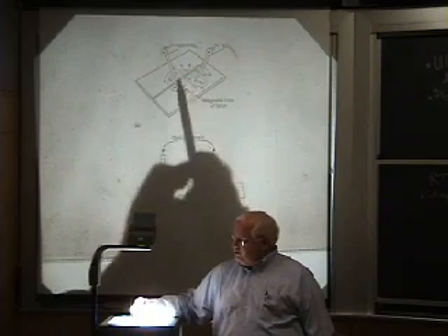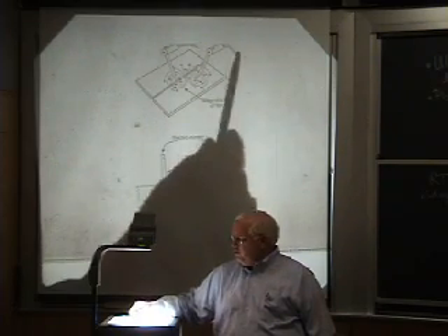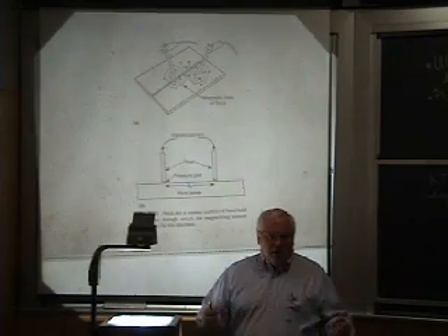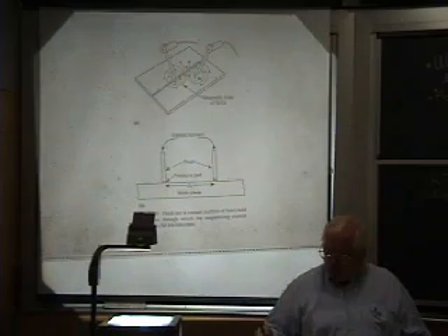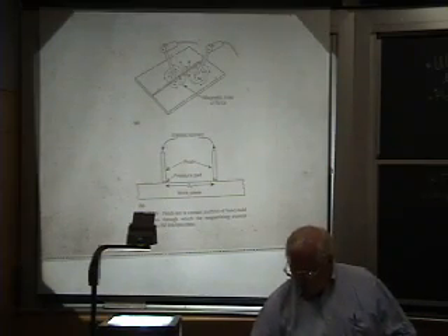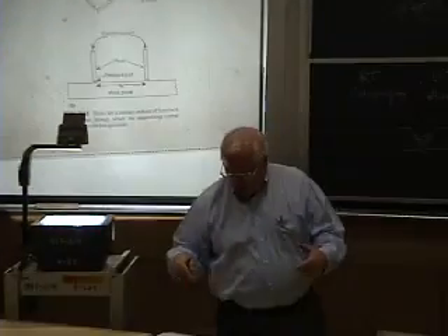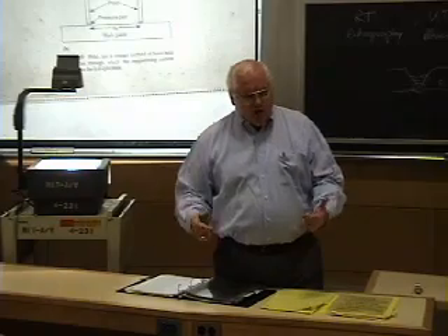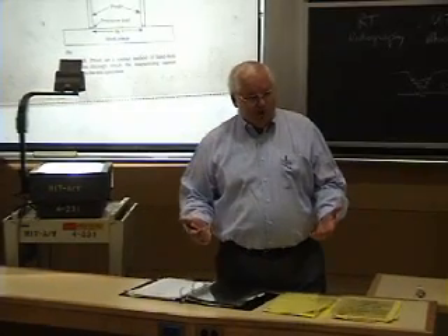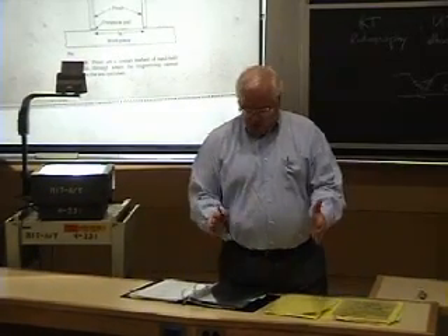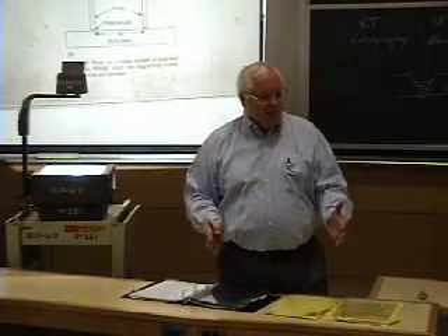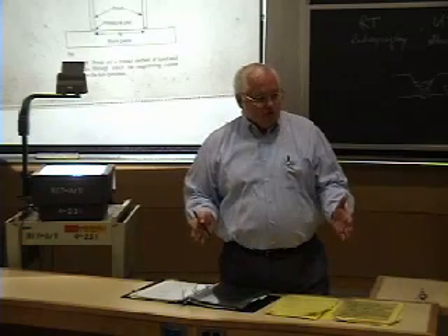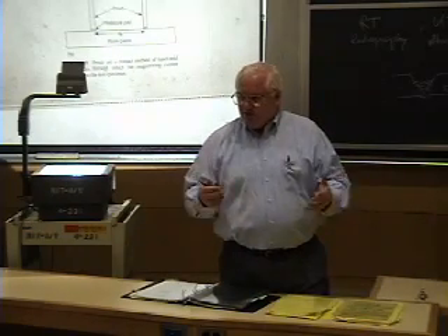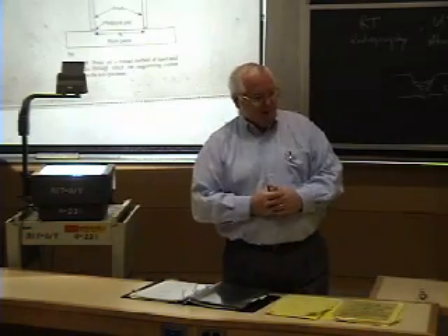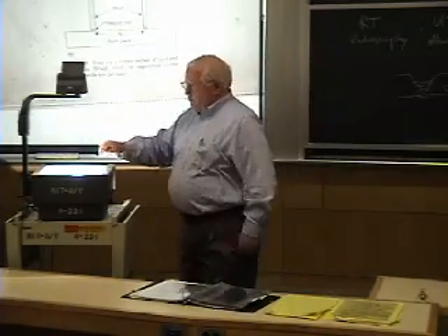But for others, like a simple half-inch or 1-inch thick weld, you can go in there with these magnetic prods, and they're just copper or carbon rods that you come down and touch to the part, and you pass a current through the thing. Now the current might be 1,000 amps. The power supply may not be any bigger than this, because you're only talking a couple of volts, because it's basically sort of a dead short. You're just trying to put a bunch of current through there.